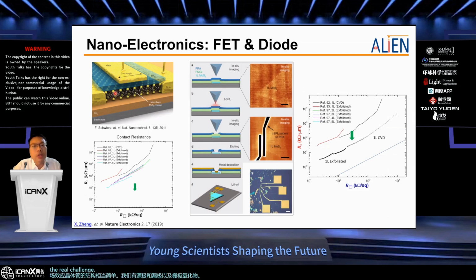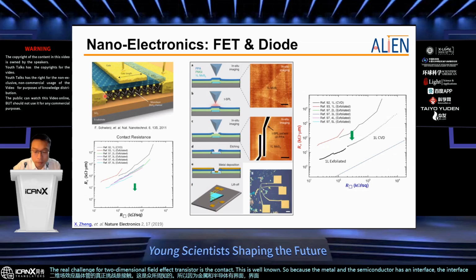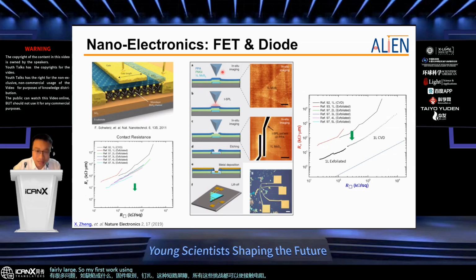The real challenge for two-dimensional field effect transistors is the contact. This is well known. Because the metal and the semiconductor have an interface, the interface has many problems like defects, Fermi level pinning, the Schottky barrier, all this kind of thing, and these challenges make the contact resistance very large. So my first work using scanning probe lithography is to improve the contact resistance by modifying, or by controlling, the quality of the interface between metal and two-dimensional materials.